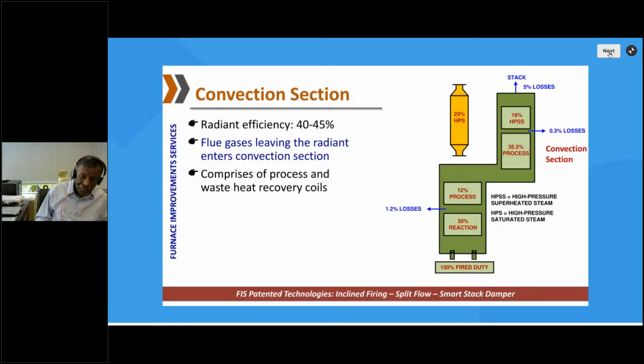Well, let's move on to the convection section. As we have said, radiant efficiency is only around 40-45%, out of which 30% is used in the reaction and 12% is used approximately in the process preheating. And then these flue gases leave the radiant section and enter into the convection section. In the convection section, we are talking of preheating the process, which again is about 35%. And then 16% is used in high pressure steam generation, high pressure steam superheater. And then the stack losses are only about 5%.